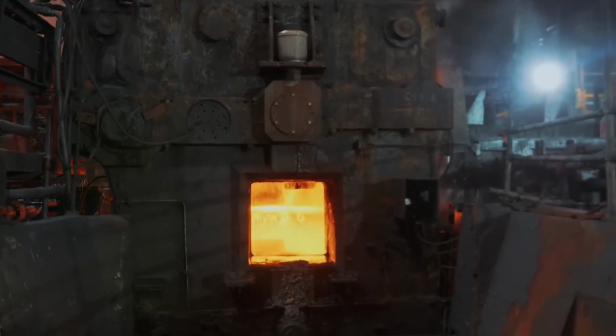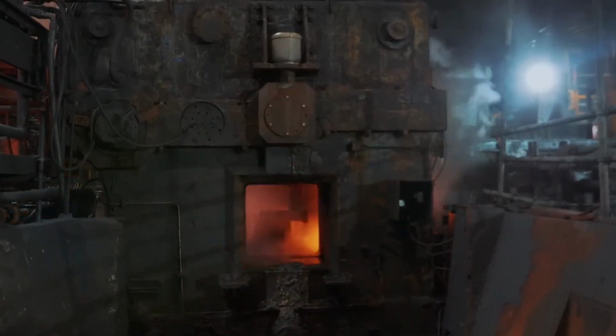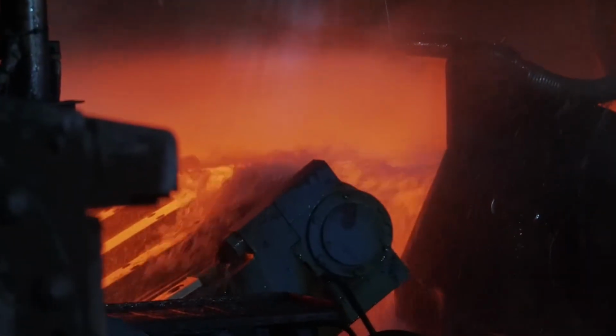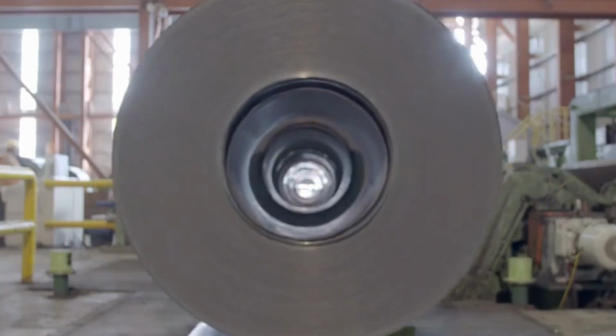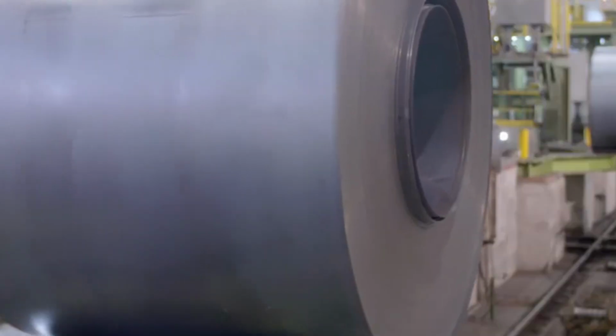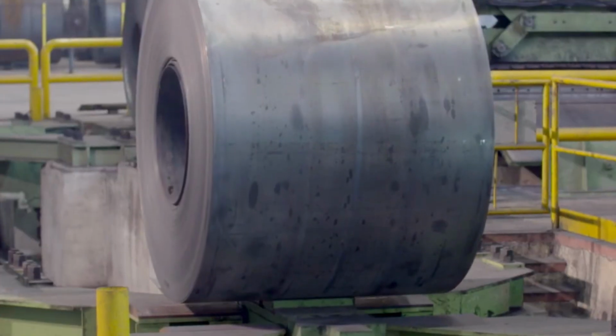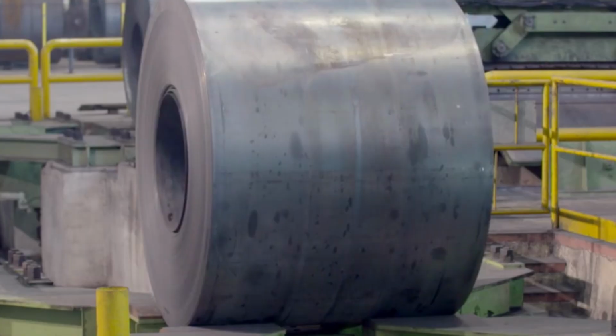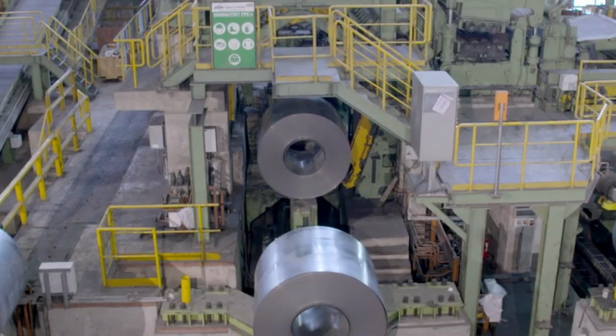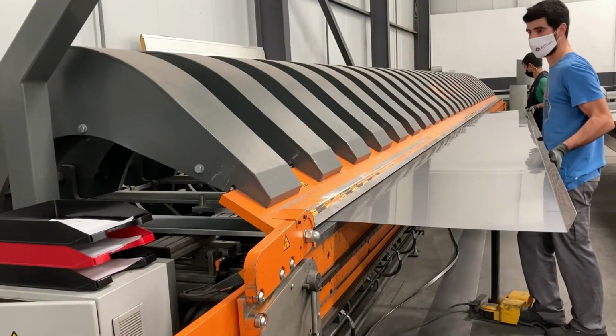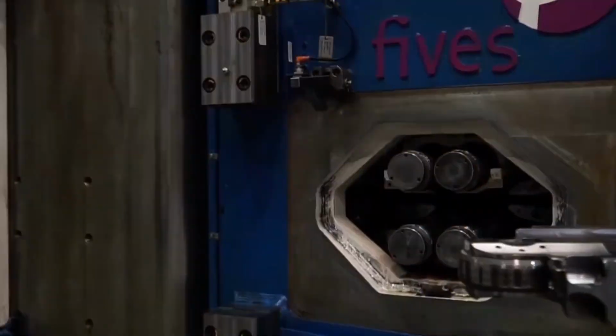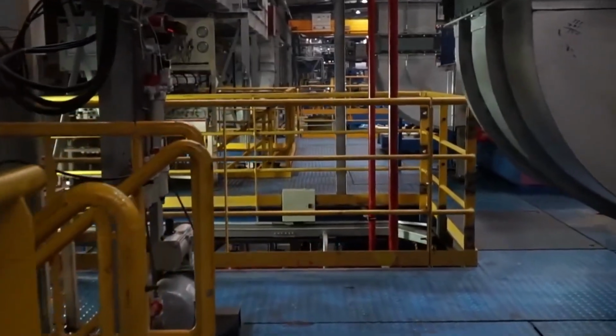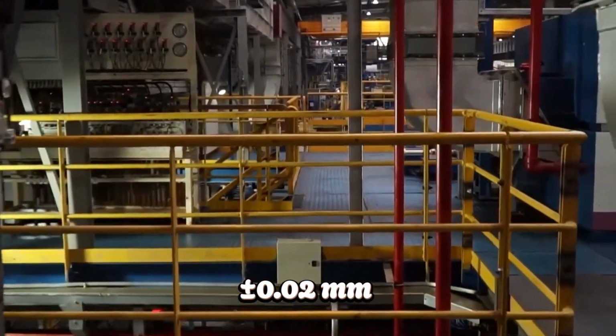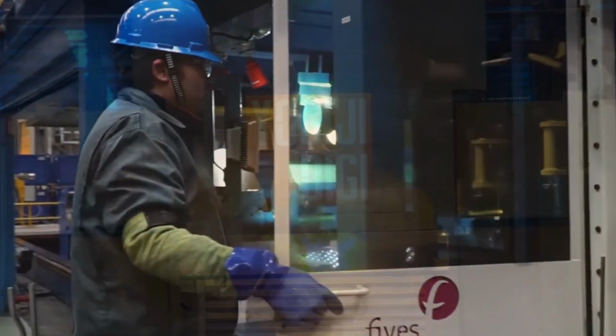Cold rolling reduces steel thickness by up to 80%, while holding flatness within 0.5 millimeters per meter. If any tolerance slips, force, tension, temperature, chemistry, the entire coil fails downstream. Today, pickling, tandem rolling, annealing, temper rolling, final QC. Modern AGC corrects roll gap to plus or minus 0.02 millimeters every millisecond.